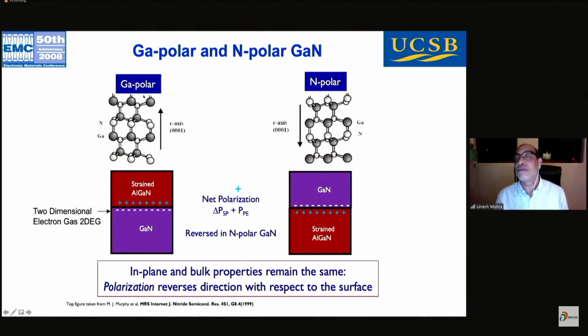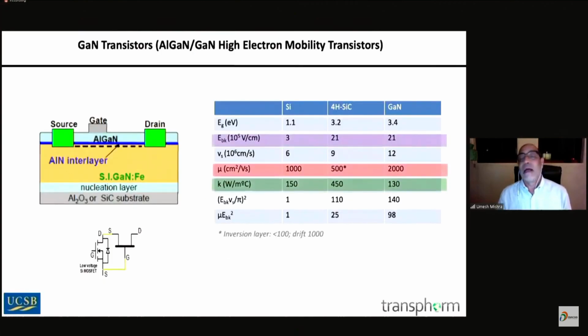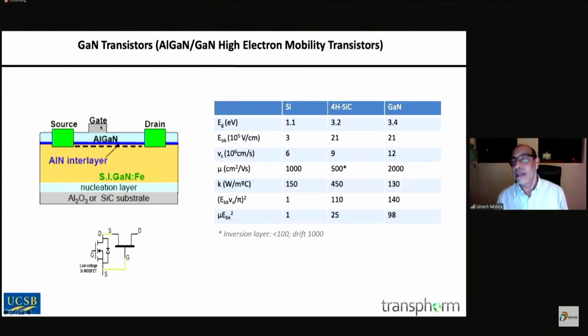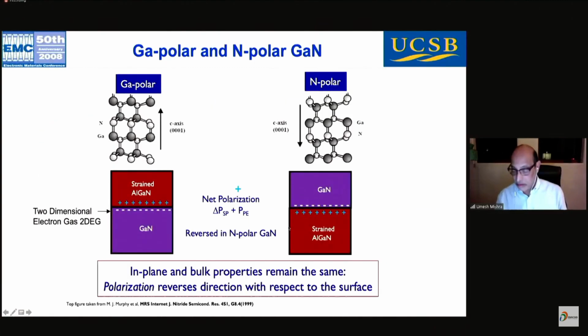There are two forms of gallium nitride. One is gallium polar and the other is nitrogen polar. And it looks much like a MOSFET. So when you have aluminum gallium nitride on gallium nitride, you end up with this electron gas, and you have a source, a drain and a gate, and current flows from source to drain in a material which has very high mobility. If you look at the mobility of electrons in gallium nitride, it is 2000, compared to that of silicon, which is about 100 in the inversion layer.